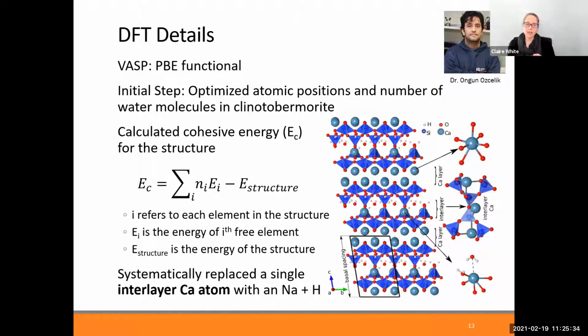created was we calculated what was called the cohesive energy for the structure. And so the cohesive energy for the structure gives you an idea of how much energy the system gains, or how it reduces the ground state energy by having the atoms bonded together in the structure as opposed to isolated atoms. So that's the cohesive energy for one structure. And it means that if you compare cohesive energies, you're able to compare structures of different chemical compositions.